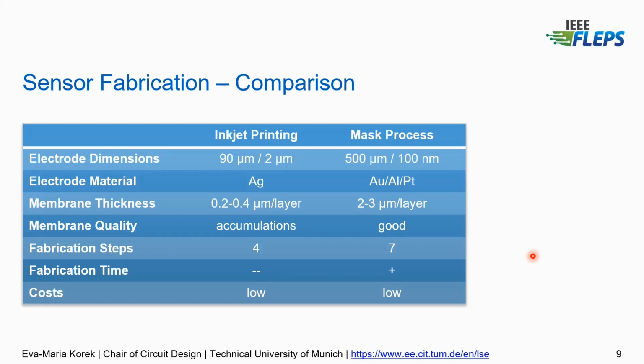And now to compare these two methods, they both have their strengths and weaknesses. So with the mask process, we have an increase in the electrode dimensions, but we have the advantage of being able to use gold, which is biocompatible compared to silver. And the membrane thickness is increased by a factor of 10, which is actually advantageous for these electrode dimensions.